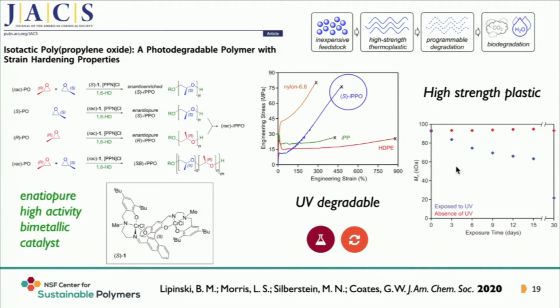So here's a plot that shows in the absence of UV, it retains molecular weight over many days, but in the presence of UV, you start to break down molecular weight. And once the molar mass of the polymer breaks down low enough, arguments can be made that it can be assimilated in the environment. So here's an opportunity of a very competitive material that ultimately ends up being UV degradable, which could play a key role in, for example, places where polymers get into the environment indiscriminately.